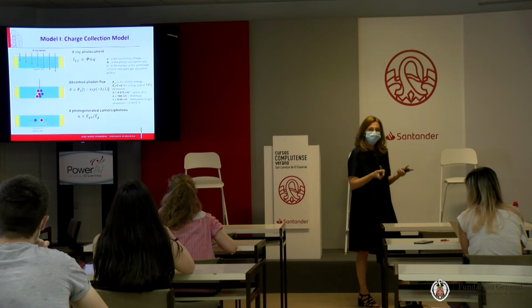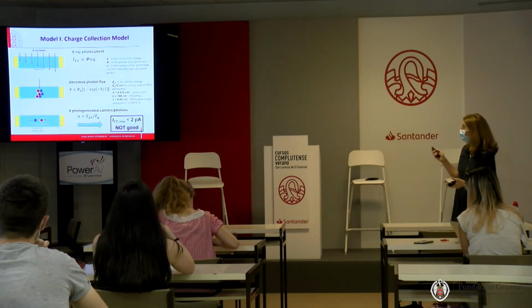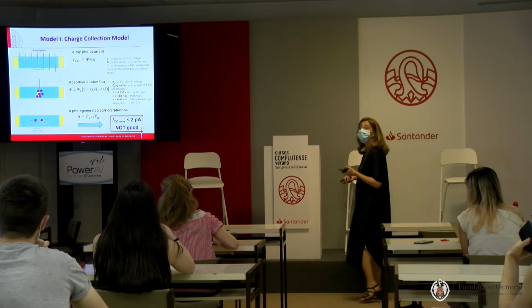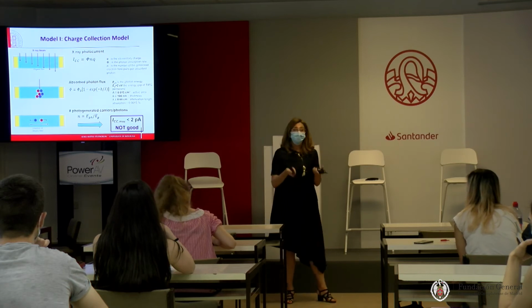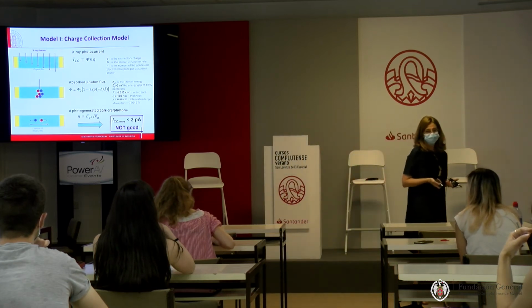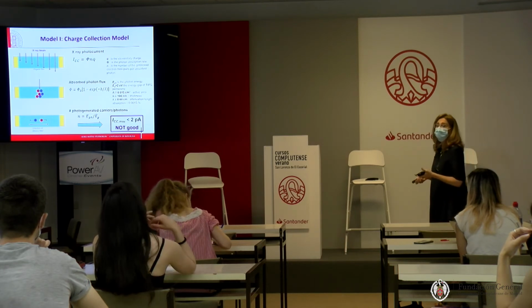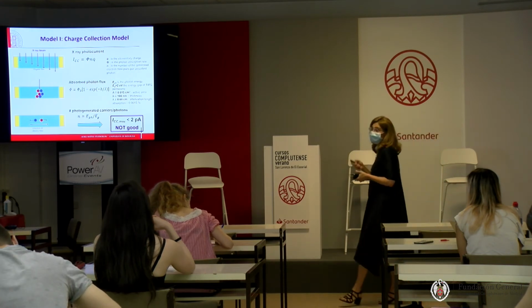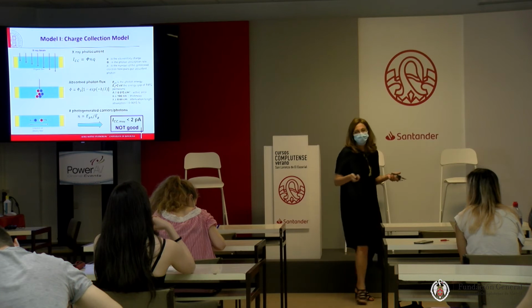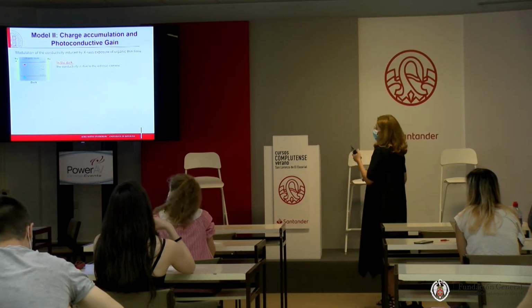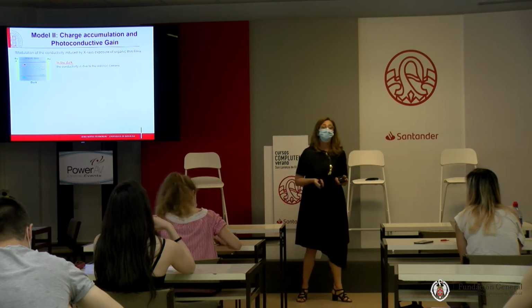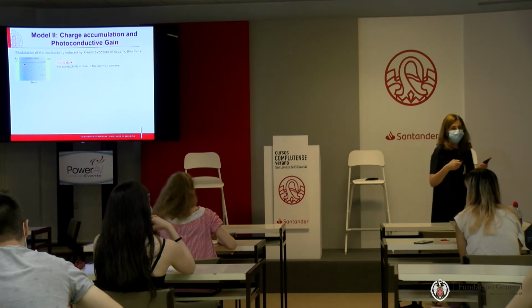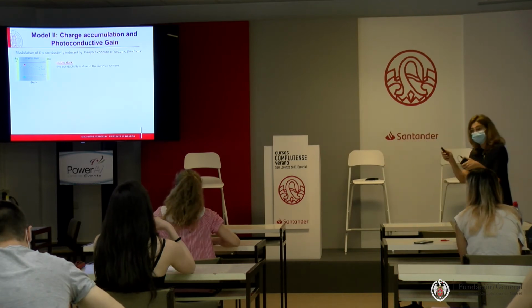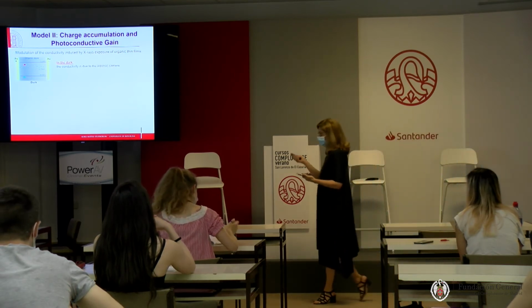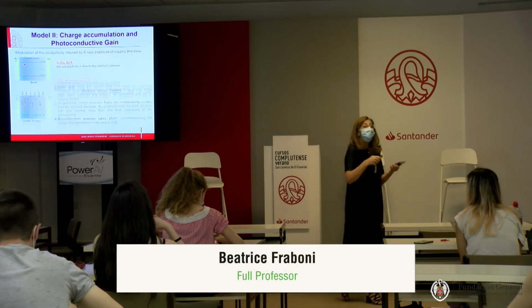If we calculate what we should see in these thin films of organic material, we would collect a current which is less than 2 picoamperes, which is not good because we are actually collecting a current which is of the order of nanoamperes. So that means that this model is not working and that something should happen because in principle these materials so thin with such low atomic numbers should not be able to absorb any X-rays. Why are they working? They are working because what happens is a photoconductive gain process. So here the defects and the traps at the interface of the thin organic film and the dielectric of the substrate play a very important role in trapping one of the 2 photogenerated carriers, typically electrons.